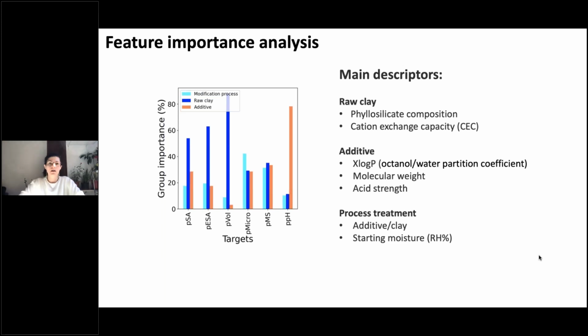Going deeper, the raw clay group of features is affected mostly by the phyllosilicate composition and cation exchange capacity, while the octanol-water partition coefficient, the molecular weight, and the acid strength are the most important features in the additive group of features. Then the process treatment features are pervasively affected by the additive to clay ratio descriptor and the starting humidity.